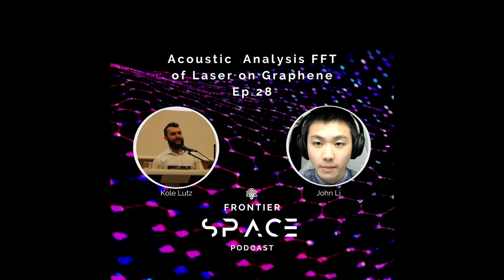Now, this is a very powerful technique because looking at SEM and Raman, the maximum that they could probably analyze in one sitting is probably on the order of maybe a millimeter maximum. But this allows you to cover meters squared, like entire samples. So that means that this is effectively a million times scale up in the throughput and in the rate of our analysis and in our capabilities to know what we are forming at every single point, at every single moment in every single sample that we are forming.